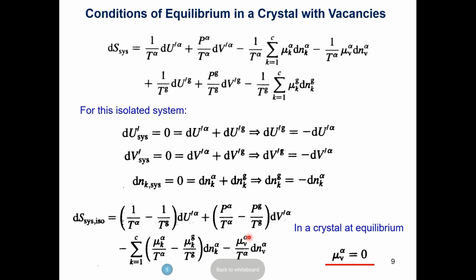This illustrates that if you create an equilibrium among the point defects in the solid, always remember the chemical potential associated with those vacancies will have to be zero, not non-zero. Unless you make a sample with metastable defects, meaning you pick a high temperature, do something like quenching, and create an amount of defects that are not the equilibrium amount, that defect concentration will change during application, over time.